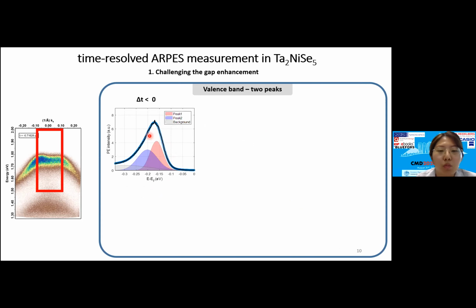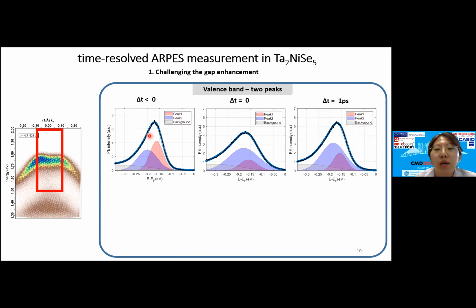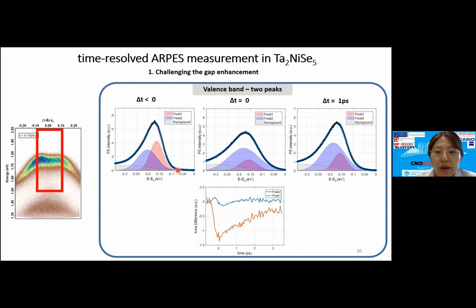this first band is not fitted with only one single peak, but we need at least 2 peaks. Regarding the dynamics of the peaks, both peaks are broadened after the pump, and the intensities of those peaks are different. This red peak is strongly suppressed after the pump. So that means the center of this first band can be shifted from the red peak to the blue peak after the pump. So in our measurement we are more in line with the interpretation of the Tokyo University paper, because we always have this spectral weight pushing into the gap.